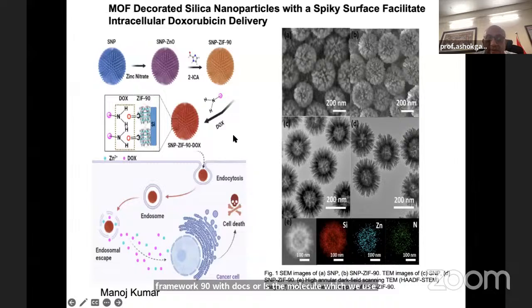Okay, this is the work of Manoj Kumar. He did his PhD jointly with me and Michael Yu in University of Queensland. So what you can see is that once you have the silica nanoparticle ZIF90 doxorubicin, you can see the loading capacity. You can see that we can have the particles circulate in the system and release at acidic pH. As you see, the environment near the cancer cells is more acidic. So the particles sustain the normal bloodstream and can be available for much more time till they go to acidic environments. So that release is at 4.5 pH.